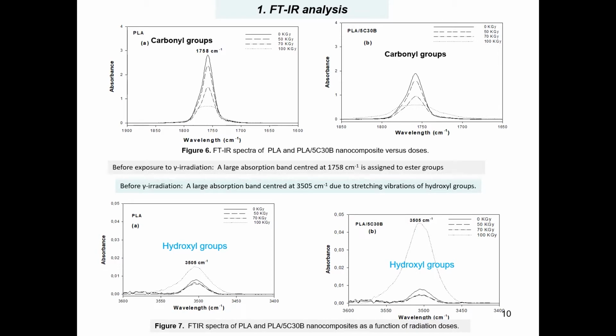We can see in figures 6A and 6B the neat PLA and the PLA-based nanocomposite before exposure. These figures are recorded in the carbonyl region. Before exposure to gamma irradiation, we can observe the presence of a large absorption band centered at 1758 cm^-1, which is assigned to the ester groups of the polymer. And we can notice also in figures 7A and 7B, in the hydroxyl region, the presence of a large band centered at 3505 cm^-1, which is due to stretching vibrations of hydroxyl groups.